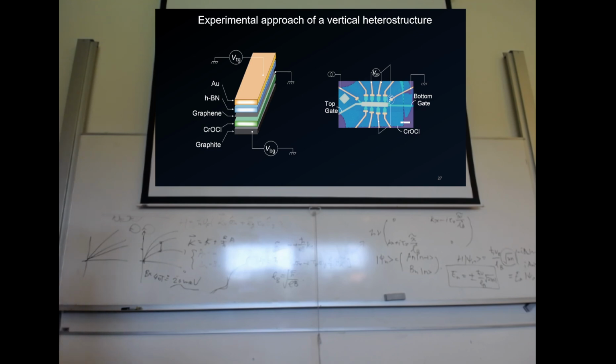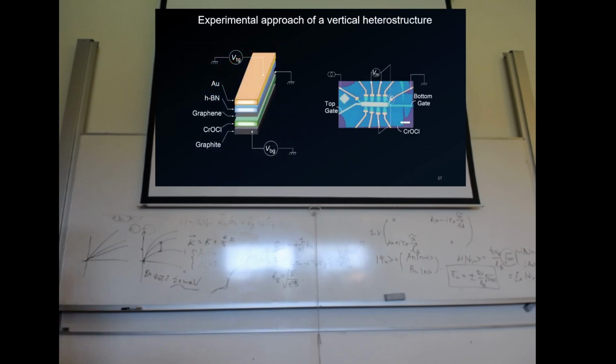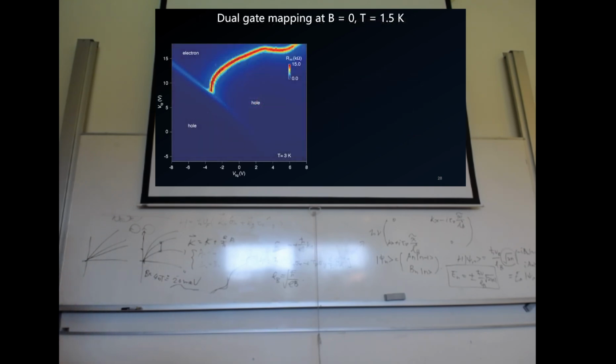This is the whole bar structure at the end of the sample. The scale bar is about, I think, either 5 micrometers or 10 micrometers, I don't remember exactly. Then we got the result of the dual gate mapping again. We saw yesterday, for bilayer graphene or monolayer graphene for example, that the Dirac peak, which is the minimum of the density of states, should be diagonal for the conventional case. But in our setup, where you just replace one of the substrates with chromium oxychloride, the whole thing is changed.